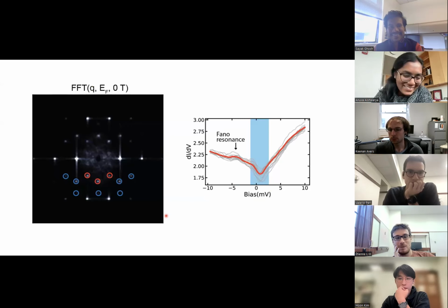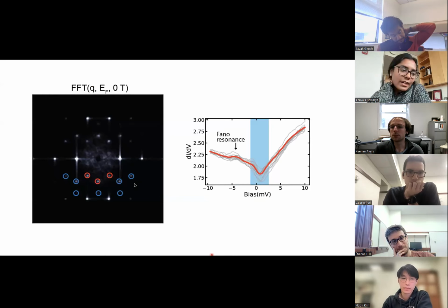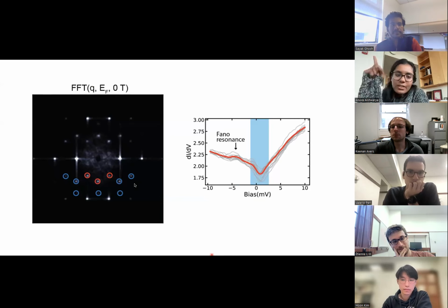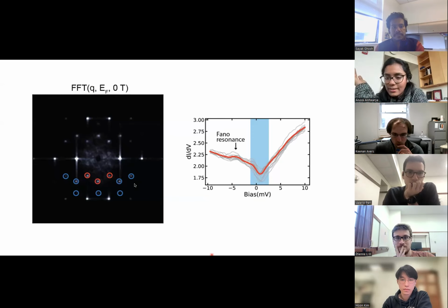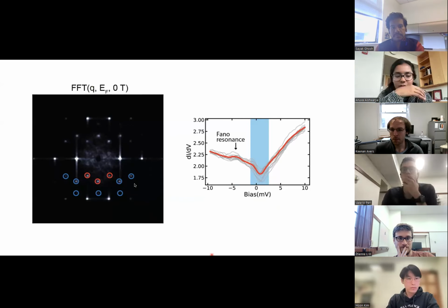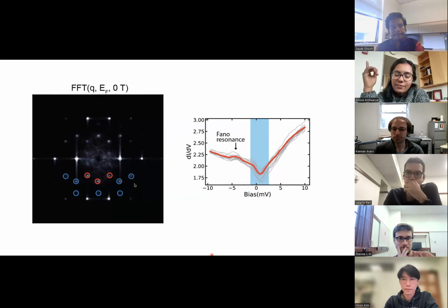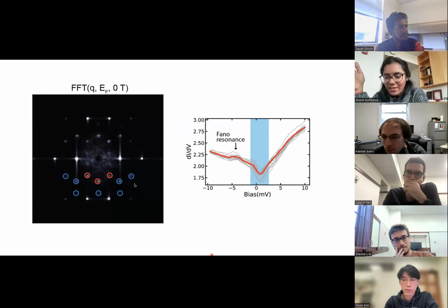Thank you. You mentioned also something about the spin triplet nature of the order parameter being crucial for your vortex physics. It's only crucial if you consider the difference between a perpendicular magnetic field versus a tilted magnetic field. So at 10 Tesla in a perpendicular magnetic field, the CDW still survives, but in a tilted magnetic field, the CDW goes away. So what we expect is that if we had access to higher magnetic field along the perpendicular direction, then we would eventually reach HC2 and kill the CDW.